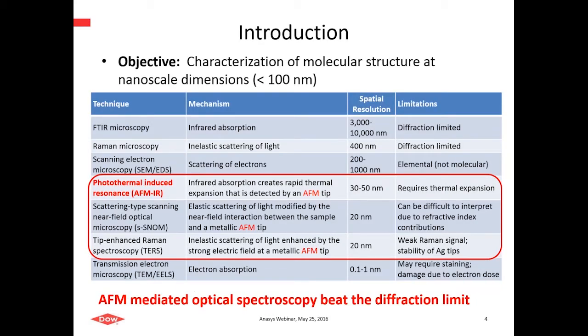Now at Dow in the last few years, we've had an internal development program to characterize chemical functional structure at nanoscales, and spectroscopic mapping at these scales is possible using some of the methods shown in this table. For example, in the electron microscope, we can use electron energy loss spectroscopy at high spatial resolution. One could go to a synchrotron using X-ray absorption spectroscopy to get very highly resolved spectral information. But the last 5 years have seen commercialization of some of these AFM-mediated techniques that bring vibrational spectroscopy beyond the diffraction limit, and those are in the red box shown here.